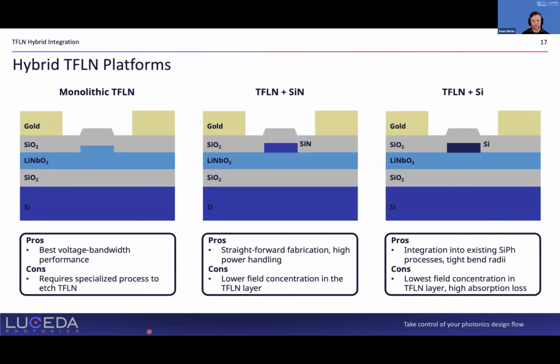Finally, I'd like to just touch on some of what I call hybrid integrations or hybrid platforms that we can achieve using thin film lithium niobate. On the left here is what I would call monolithic thin film lithium niobate, or a single material for our waveguide. That single material, of course, lithium niobate. This is the best for voltage bandwidth performance, meaning as we increase our voltage, generally we will decrease our bandwidth. So it's sort of an inverse relationship where generally we want as low a voltage as possible and as high a bandwidth.